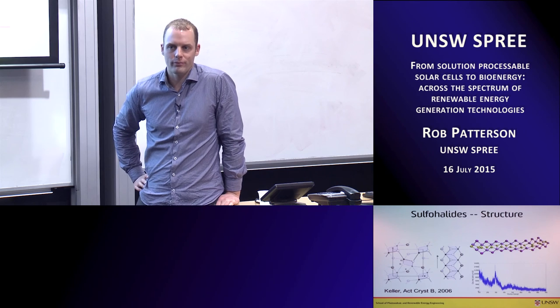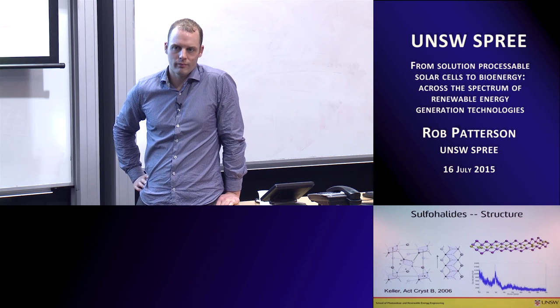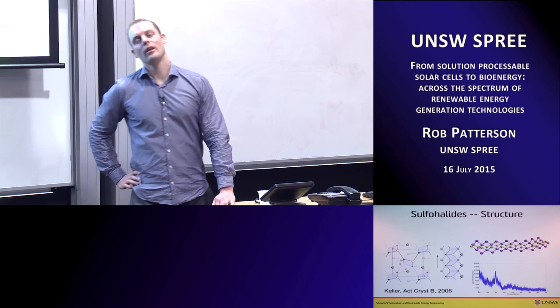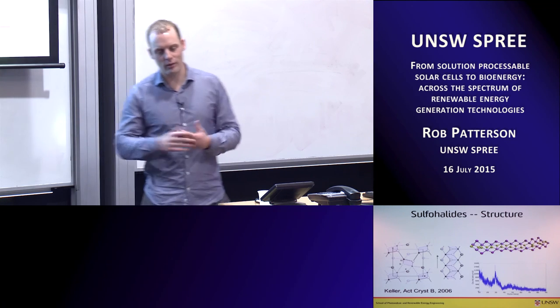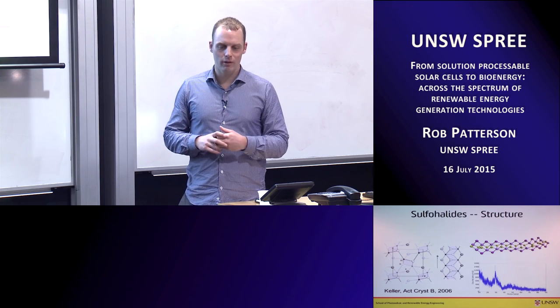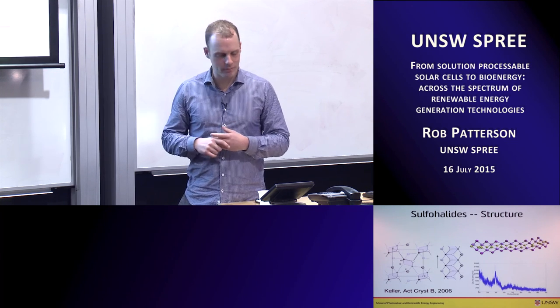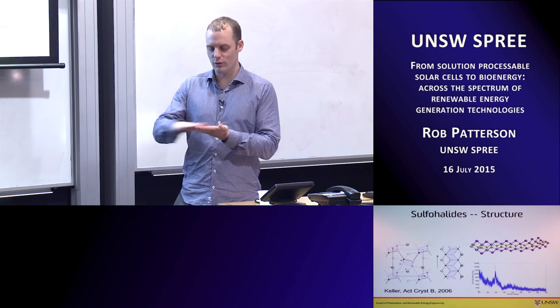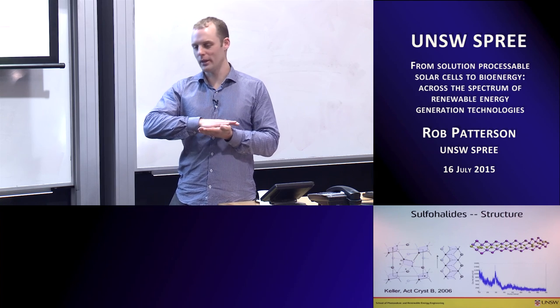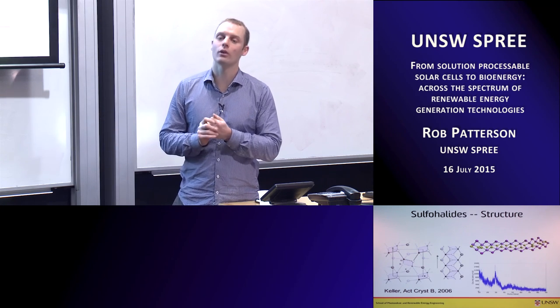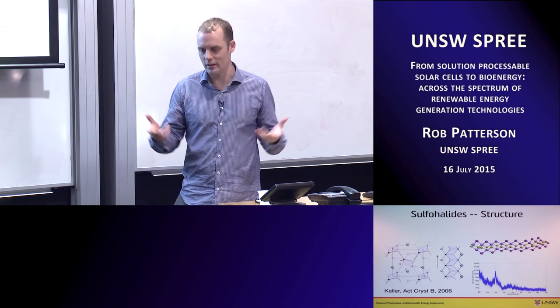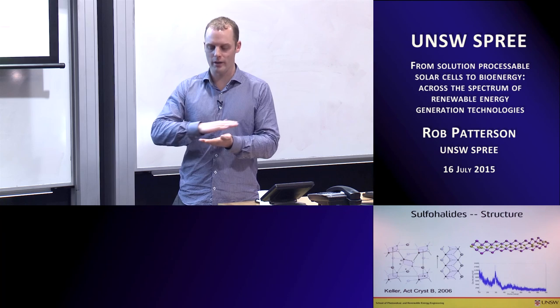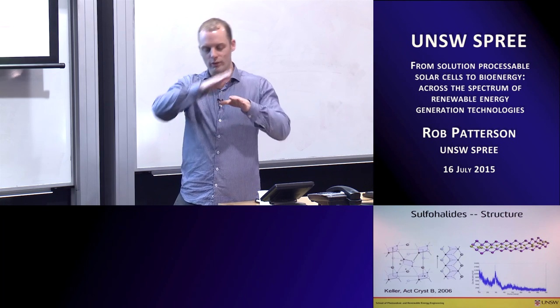Okay, so in that case, when you replace a long ligand with a very short ligand, wouldn't you be introducing a strain and maybe possibly tear in the surface, because now you have some quantum dots coming together, some going apart? Definitely we do. So you have a volume contraction, right? Yeah. Because you're exchanging these long chain ligands. And so definitely the first few layers have big gaps. And that's why you make another layer on top. So when we do the spin coating, we tend to try to repair those. People repair those cracks by spinning another layer down and doing the linking again. And then hopefully you fill in those gaps, right?